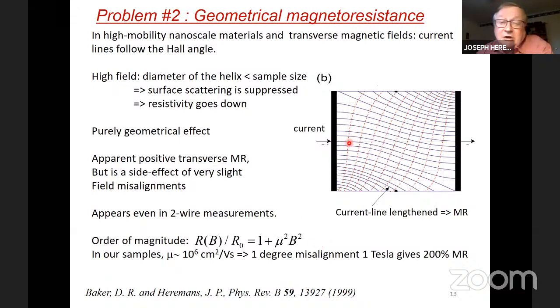If we had an infinitely long, infinitely wide, I should say, and very narrow sample, that geometrical magnetoresistance would be proportional to 1 plus mobility squared times field squared, which would mean that if we had, for example, in our samples, 1 degree of misalignment of the field, where the field comes out of the plane of the drawing here, that would give us, with a million mobility, 200% positive magnetoresistance, which swamps out all the data. So this is a very serious problem that has to be taken into account, again, by looking at the geometries and at the misalignments of the samples.